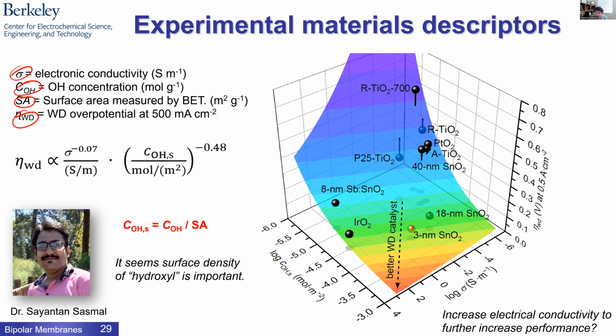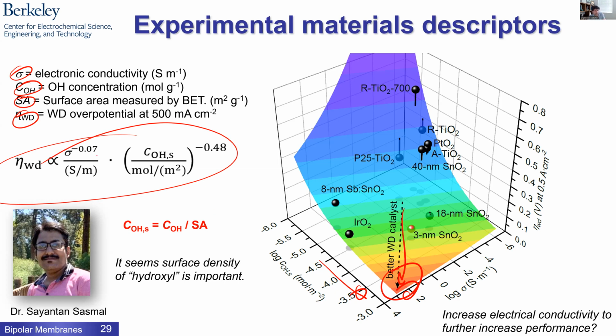And certainly if you plot that all on a three-dimensional plot, it all sort of drives you to better catalysts down in this corner: high conductivity and high surface hydroxyl coverage. You can fit that to an analytical expression. It's just a fit. So these things don't necessarily have any physical meaning except for the dependencies found in this fit, but it all sort of makes sense that those are the parameters, and it holds when you look at many different materials. You anneal them at different temperatures, et cetera, and you measure these parameters.